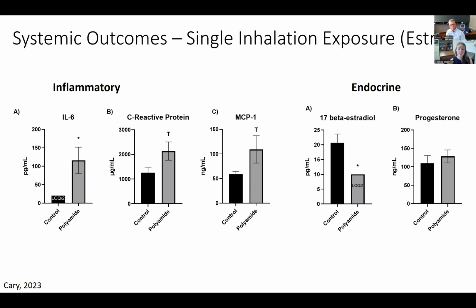We also evaluated the endocrine system, and that was probably the most interesting component for my end, because polyamide is not known to have a plasticizing chemical. It isn't known to use phthalates or BPA or things of that nature that are known endocrine disruptors. It actually uses water as its plasticizing agent to change the flexibility. But even in that case, we found that there was a significant reduction in 17-beta estradiol, which is an estrogen mimetic that's necessary during pregnancy. And again, this is the most fertile time point. So we do have some questions about fertility after this micronanoplastic exposure.